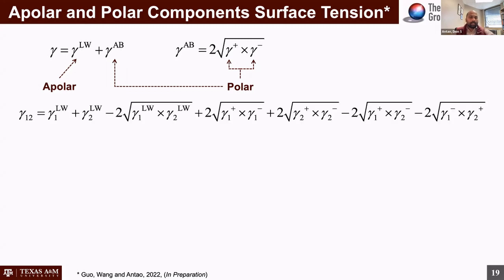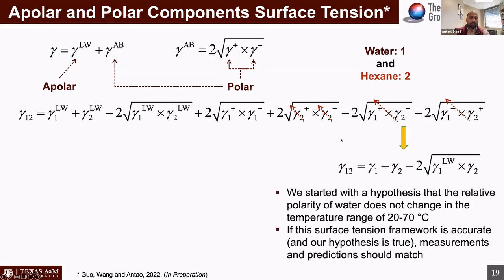When you have two fluids interacting, fluid 1 and fluid 2, you have this larger expression that explains the interfacial interactions. But if fluid 1 is polar, like water, and fluid 2 is completely nonpolar, like hexane, the nonpolar fluid has no polar components, and so your equation reduces down to something that's fairly easy to test. You basically have one equation, one unknown, and because the interfacial tension is something that you can measure.